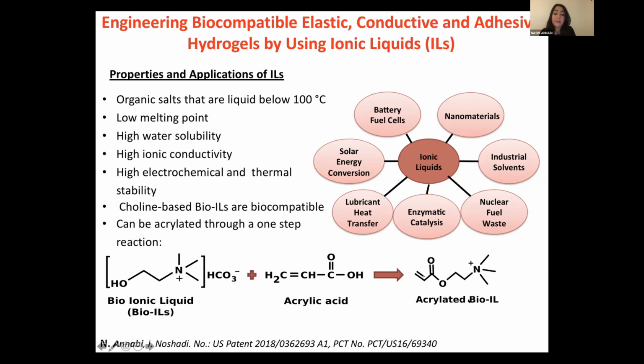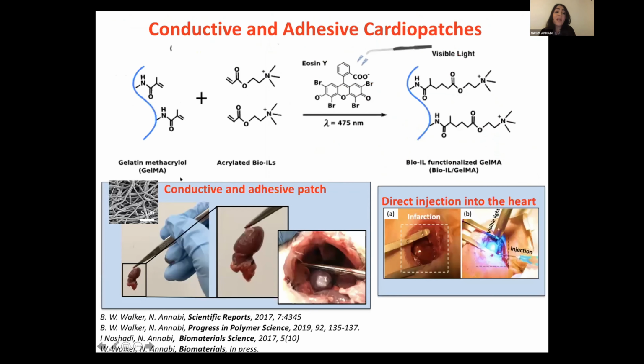So for the first time, we use bioionic liquid, and again, through a one-step reaction with acrylic acid, we form acrylated bioionic liquid. Once we form this modified bioionic liquid, it can be combined with different type of polymer that are functionalized in the same way by mixing different ratio of acrylated bioionic liquid with any different biopolymer. Here, I put gelatin methacrylate or GELMA as an example. You can add photoinitiator, and by using visible light, you can form bioionic functionalized polymer that has conductivity, and you can finely tune the level of the conductivity in this biomaterial.